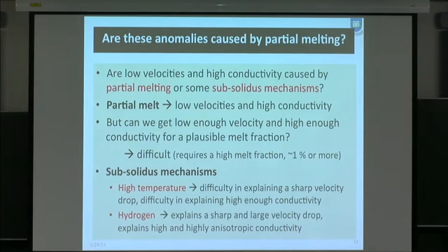So the question is, given those anomalies, are these anomalies really caused by partial melting or by a subsolidus mechanism? Obviously, partial melt causes low velocity because melt is soft, and melt has high conductivity. But also there are some subsolidus mechanisms which could explain those anomalies, like simply high temperature causes low velocity and high conductivity, and hydrogen can also reduce velocity, hydrogen makes material soft and highly conductive. So those are competing processes which we need to evaluate to see which one is a more likely cause for those geophysical anomalies.